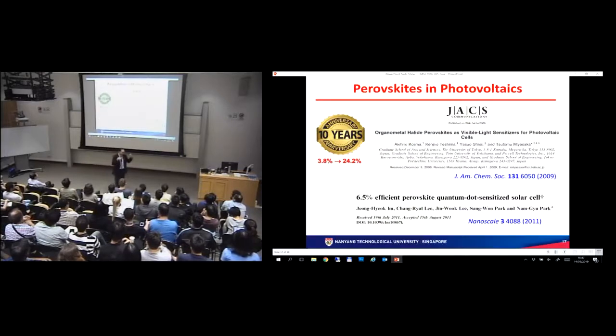Now, it had to wait for its time to come, and the time came around 2009. This year actually marks the 10-year anniversary of the invention of the perovskite solar cell. Now, the perovskite solar cell sort of splintered off from the dye-sensitized solar cells. Miyasaka was the first one who actually used this perovskite as a sensitizer in the dye-sensitized cell in a liquid electrolyte system. Obviously, the perovskite doesn't like liquid very much. It's not very stable, but he still managed to get about 3.8% efficiency.